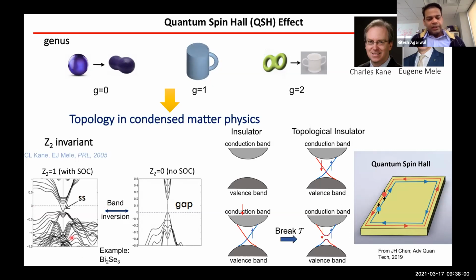And the idea here is, in a regular, let's say, trivial insulator, although they're by no means trivial, but from the topological aspect, let's call them trivial, you have a particular ordering of the bands. For example, in cadmium sulfide, the valence band is made of p orbitals. The conduction band, at least close to the gamma point, is made of s orbitals. And if the material has very strong spin orbit coupling, then you can mess up the ordering. So the conduction band can actually go below the valence band, and this is band inversion.